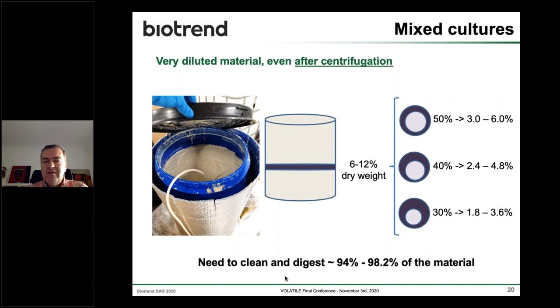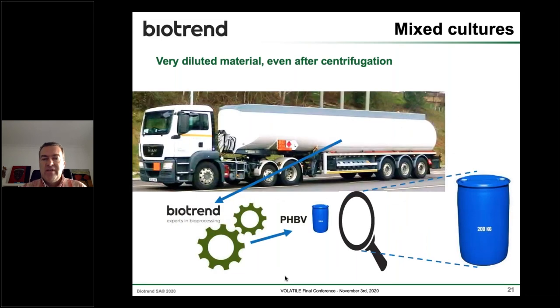So now moving a little bit to the mixed culture systems. These are very diluted systems. They have quite limited dry weight, between 6 and 12%. And taking into account the typical amount of PHA in these cultures, in the end, we need to clean and digest between 94% and 98% of the material, which is quite challenging. So if you have a truckload of this mixed culture material, you need a lot of effort and processing in order to only get a limited amount of polymer. So from a truck like this, with around 30 cubic meters of culture, you would only get 200 kilos of PHBV in the end.